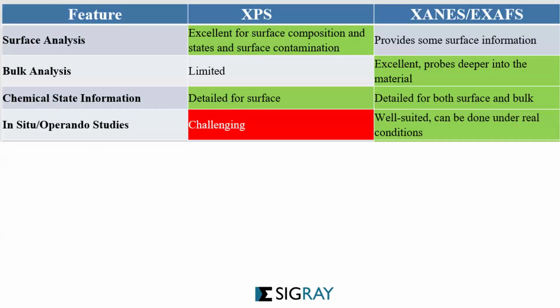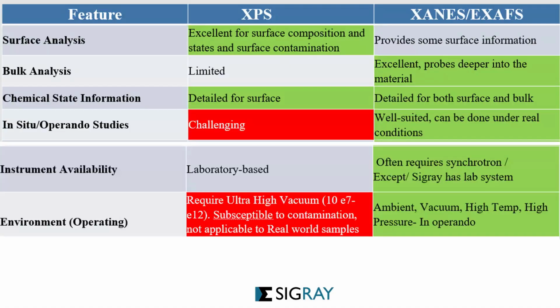In fact, XPS only looks at the top few nanometers of the material, and it is not possible to do in operando types of studies, whereas XAS, or XANES and EXAFS, give you the ability to probe not only the surface, but also the bulk. And you can do in operando studies using XAS. And XPS people know more because it's laboratory based, whereas XANES are often only available in synchrotrons, where they are doing real practical studies. Except now it is possible to do studies that in the past could only be done in the synchrotron.